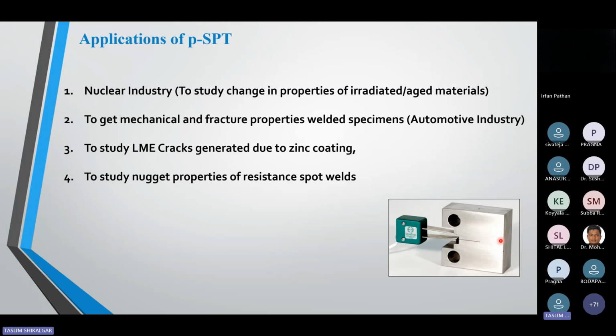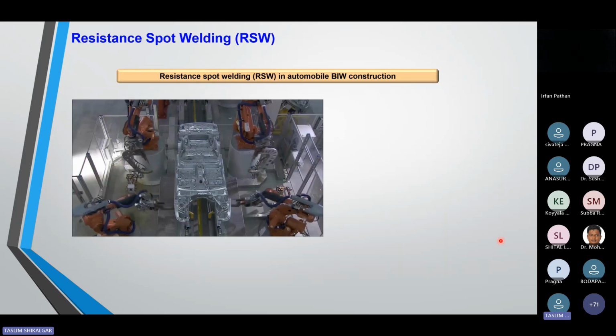Automotive industry is using this. Third one is to study the LME cracks. LME means liquid metal embrittlement, cracks generated due to the zinc coating. I will tell more about this also. And to study the nugget properties of the resistance spot welds. These are the four major applications of the PSPT. Second, I would like to show one small video.